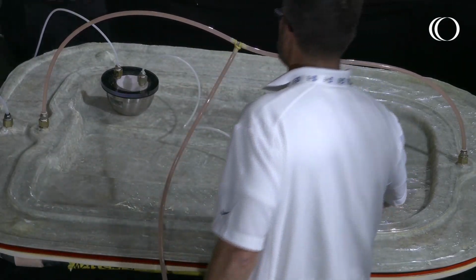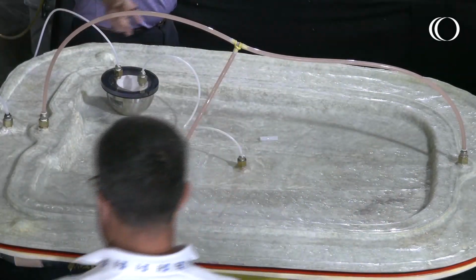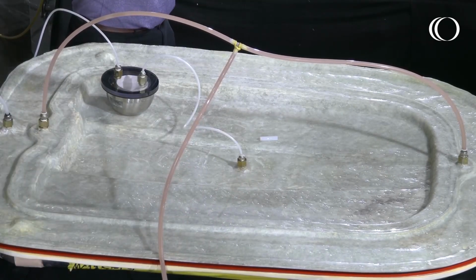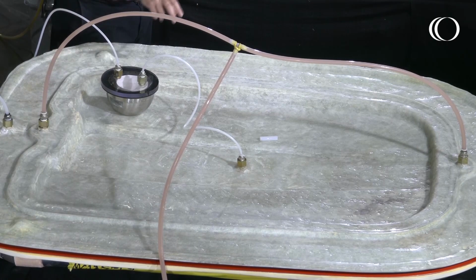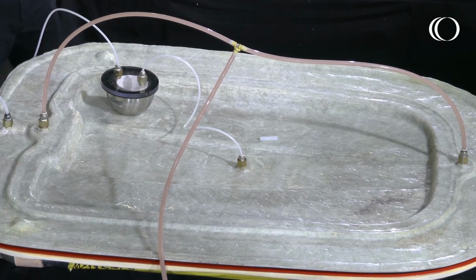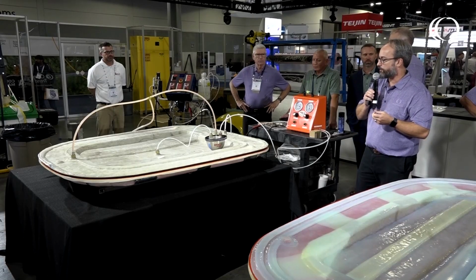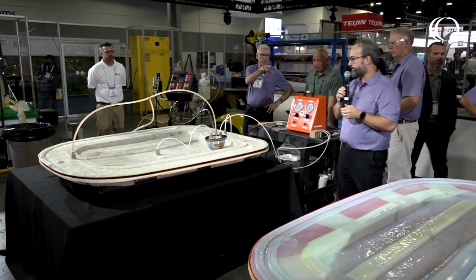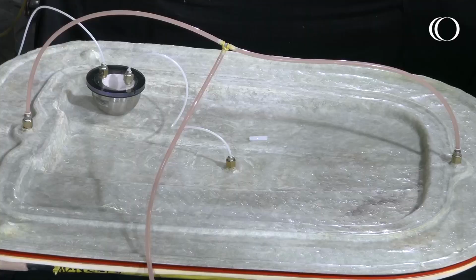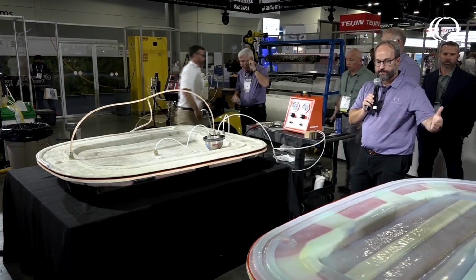You can see we have 2 feed lines coming from the machine. They're teed together, so it's feeding our resin runner at the front and the back, racing around, and it's flowing to the center. The Light RTM fill tends to be a little bit faster because our resin content's a little higher, so we have a little bit higher permeability in the mold cavity. But our resin flow front is shrinking as the part is filling. So the perimeter feed is a little bit faster flow than the center feeds.